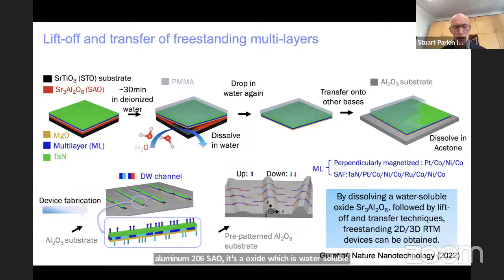So we grow this water-soluble oxide by pulsed laser deposition onto a substrate. And then on top of that SAO, we grow our racetrack. And it can be a simple ferromagnetic racetrack or a more complicated SAF racetrack, as shown on the right-hand side, these blue layers. You can see it's platinum, cobalt, nickel, cobalt, or a SAF, synthetic antiferromagnetic racetrack formed from the same platinum, cobalt, nickel, cobalt, twice with ruthenium in between.